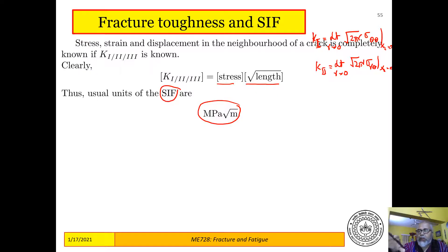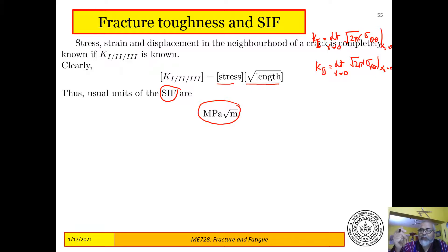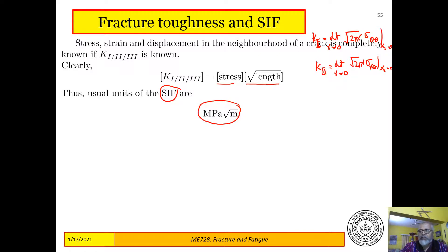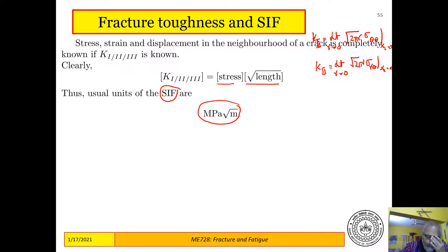This means we can envisage a situation where this parameter reaches a critical value at which the crack starts to grow. Since the crack tip stress fields determine when the crack moves, this one parameter must have a critical value for crack initiation. This is analogous to stress and yield stress — stress is applied to the body and yield stress is a material parameter. So K1, K2, K3 are the loads applied at the crack tip, and their critical values K1c, K2c, K3c are the fracture toughnesses of the material.